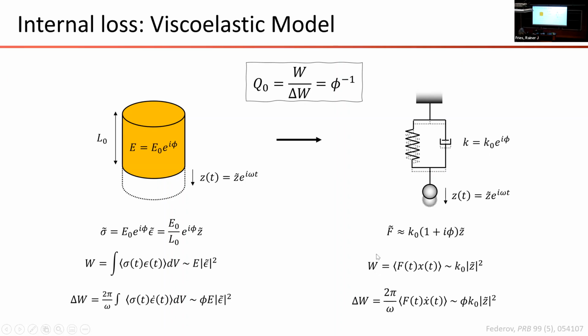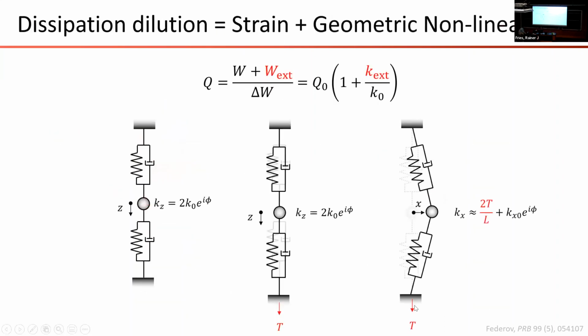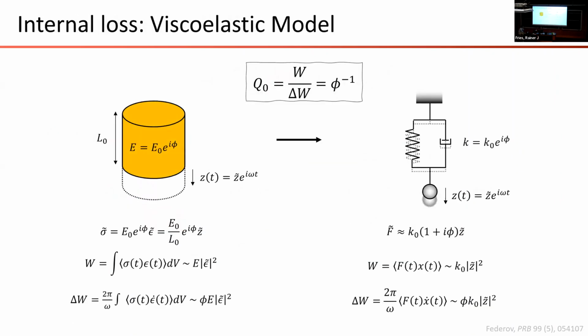What that means is that the energy of vibration of this mass suspended from the spring-dashpot system gets dissipated because the restoring force is out of phase with the force. And again, the ratio of the stored energy, the cycle-averaged force times displacement, and the energy dissipated per cycle, the cycle-averaged force times velocity times a period, is again characterized completely by this loss tangent.